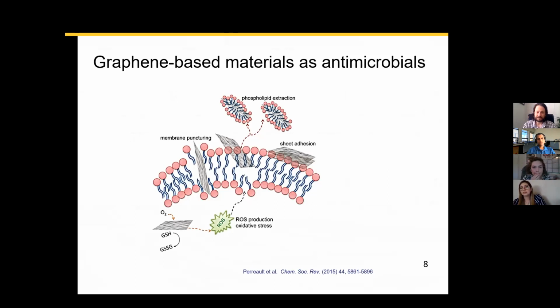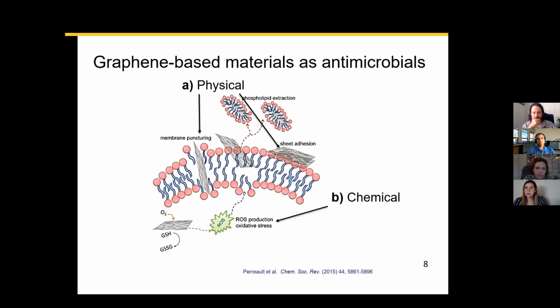agents. And so if we look in the literature, we see that there are two main types of mechanisms of interaction. We can have a physical mechanism where the graphene oxide tends to adhere to the bacterial membrane and the lipid bilayer. But because we also know that the sheet has very, very sharp edges, the materials can also cause membrane puncturing. It's also called a nanoknife effect. On the other side, we can also have chemical mechanisms where we generate oxidative stress. That's usually observed as an increase in reactive oxygen species production.